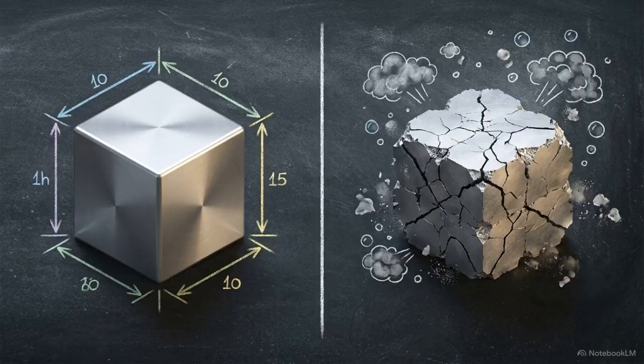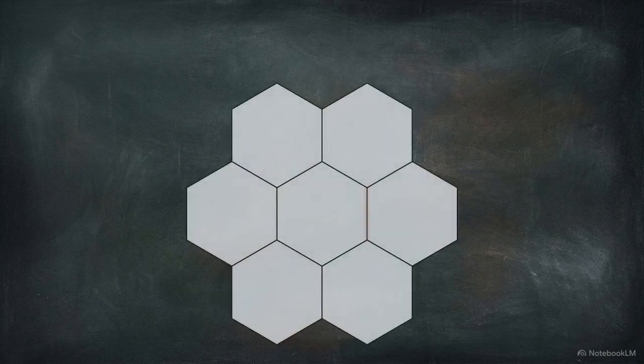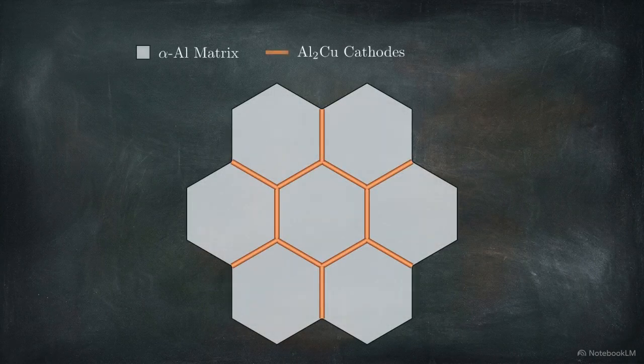This data raises a question. Why does the hardest, most optimized sample suffer the most severe structural softening when exposed to brine? The answer lies at the boundaries of the internal structure. Microgalvanic cells form between the primary pure aluminum, the alpha phase, and the secondary Al2Cu intermetallic phases.